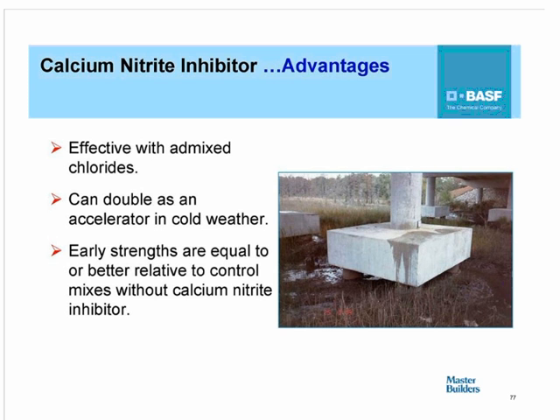Now, the main benefit of calcium nitrite is the fact that it can be used with admixed chlorides, and it also accelerates the time of set of concrete. So as a result of that, in the wintertime, it can double as an accelerator without having to add an additional accelerator to the mix.